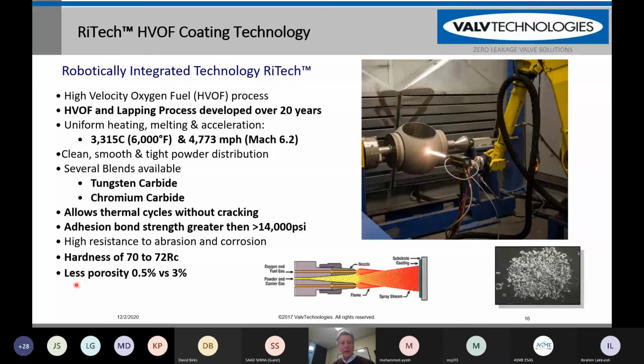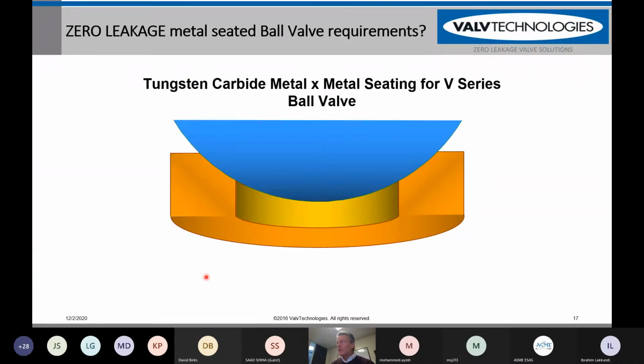Another important property of the valve, in addition to the adhesion and the hardness, is the porosity. If you have a high porosity, which means you probably do not have an adequate lapping process that you're using, you can get delamination and high friction. Our porosity is less than 0.5%, and from the measurements that we've taken from other industries and other manufacturers, it's typically greater than 3%. So you can see right here that we have a very wide seating area between our ball and our seats.